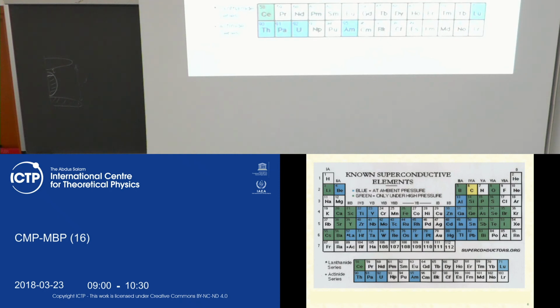But I know, for example, what I know about superconductivity of carbon. If you take graphene-like structure, which is quasi-two-dimensional pieces of carbon-based material, because carbon can form a diamond structure, which is three-dimensional. It can form graphite-type sheets. So if you take this big graphite stack, then it's superconducting if you intercalate it with some metals. So you add some metals like potassium in a little concentration, and then this graphite is superconducting. Graphene, single layer, two layers, is not superconducting at all. Yeah, this is what I know. Maybe it can be superconducting if you dope it a little bit.